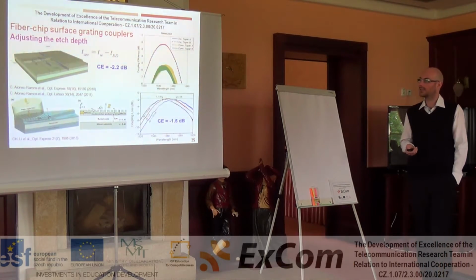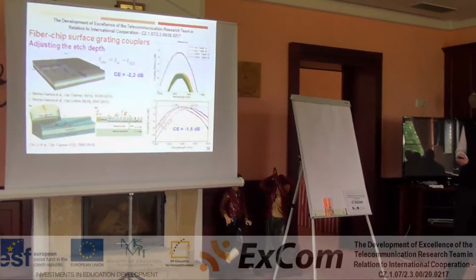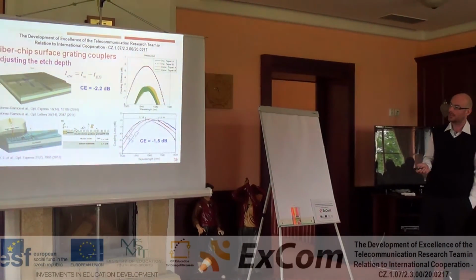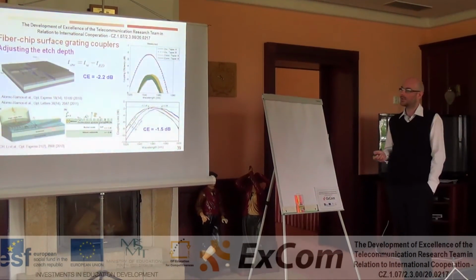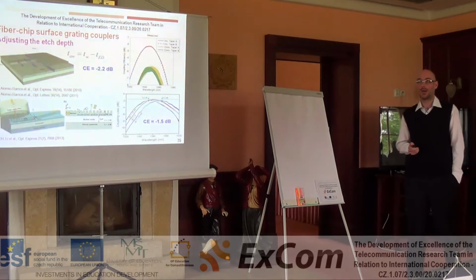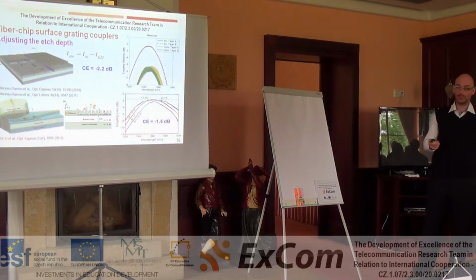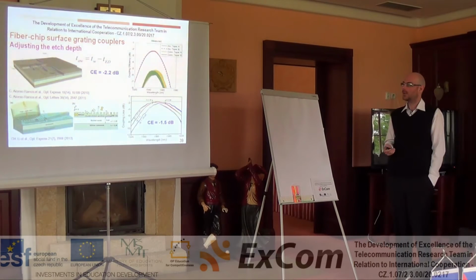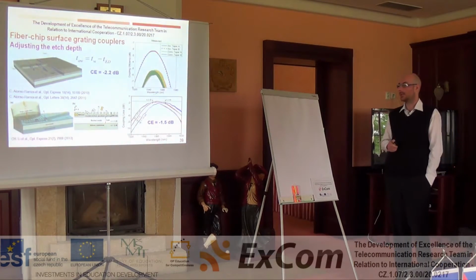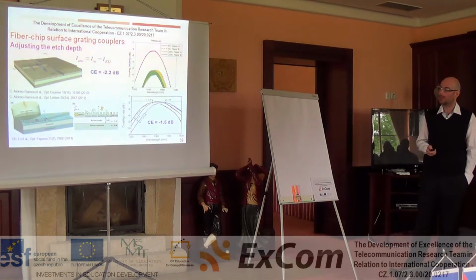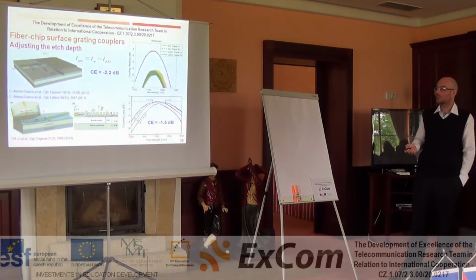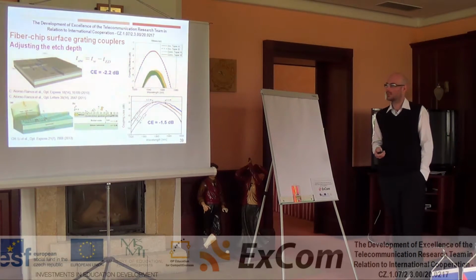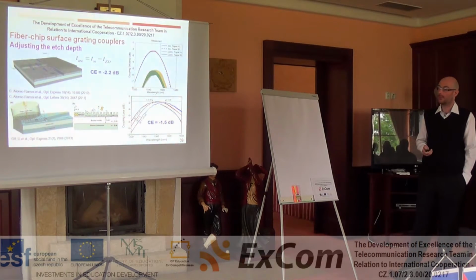The group from A*STAR in Singapore has developed a very nice grating coupler that has been fabricated by DUV lithography, and they achieved a very high coupling efficiency of minus 1.5 dB. In this case, they use two different etch depths to diffract more power from the grating.